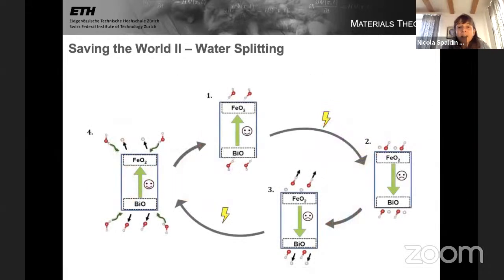And so this gives us a cycle whereby if we start with happy bismuth ferrite, we adsorb water, we switch the bismuth ferrite with an electric field, and dissociative adsorption is preferred. And of course, the ions that are disfavored, then there's a strong driving force for them to leave. So for example, the H plus ions stay on the FeO2 minus surface, the OH minus ions stay on the bismuth oxygen surface. So we've split our water, and we have a mechanism even for removing the opposite ions. When we switch back, then we're back to the happy surfaces, the charged ions leave, and we redissociate molecular water, and we can repeat this cycle.